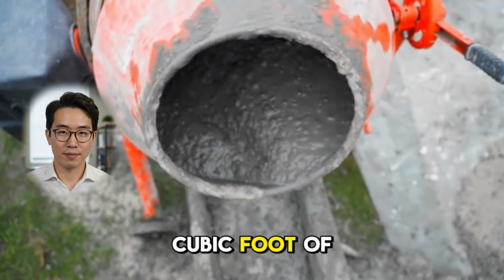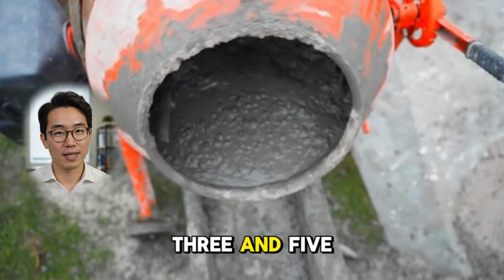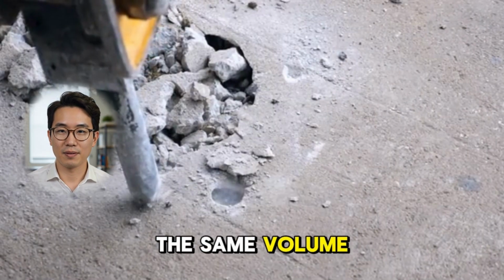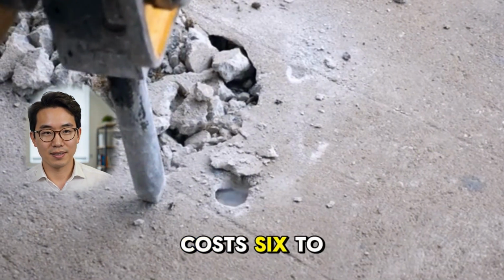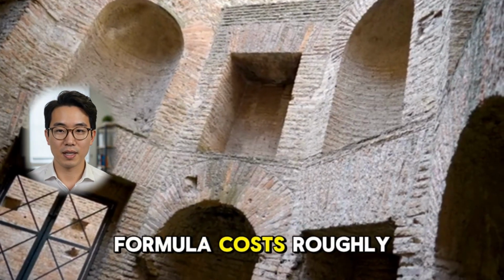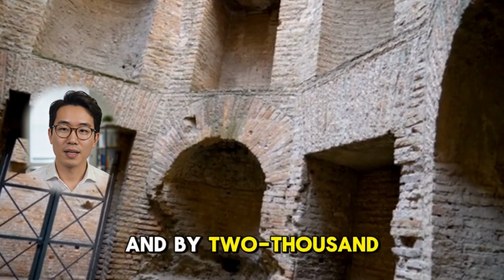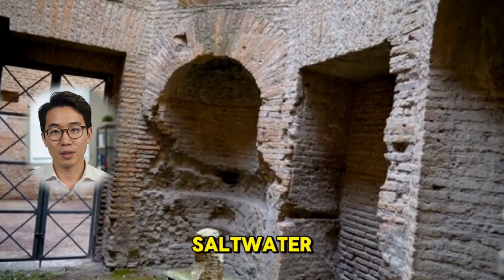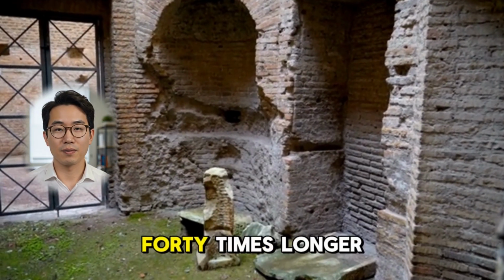The cost per cubic foot of finished mortar sits between $3 and $5. The same volume of standard Portland cement mortar costs $6 to $10. The Roman formula costs roughly half as much. And by 2,000 years of demonstrated field performance in open saltwater environments, it lasts roughly 40 times longer.